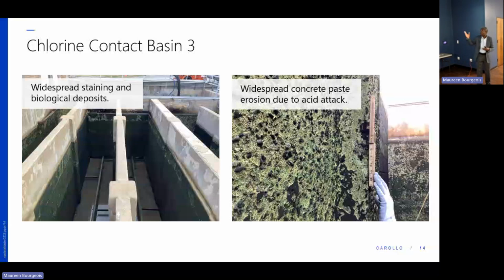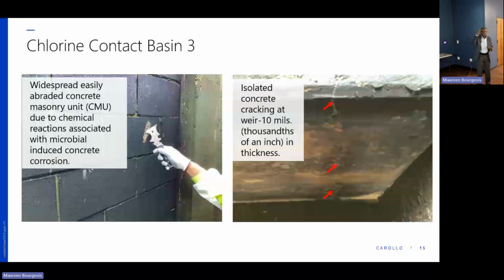So for example, in the chlorine contact basin, we had a concrete masonry unit, CMU wall in there, easily abradable. You could easily take a sharp edge and scrape it off because it's a very aggressive environment and the bacteria is beginning to eat it up. On one end, though, we also saw an isolated concrete crack, very isolated, 10 mils, thousandths of an inch. And so we captured that also in that photo.